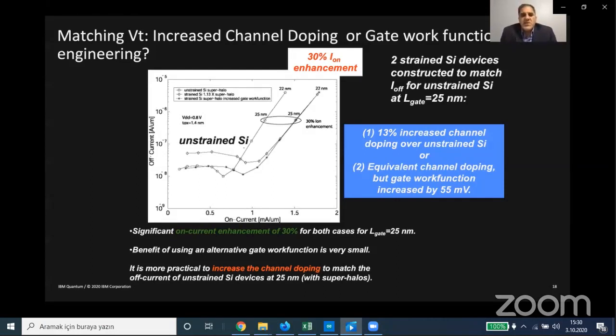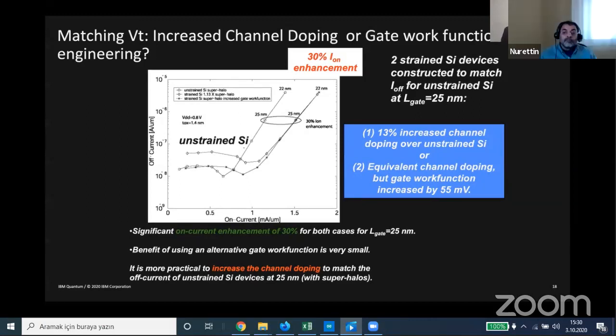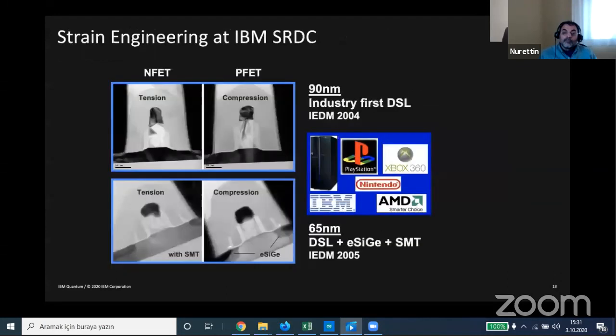And these results were presented at the IEDM conference and gave the industry confidence in using strain as a knob to boost nanoscale technology. In fact, we used this at IBM at 90 nanometer, 65, 45, 32, 22, and so on for several technologies. Shown here is the 90 nanometer. We used tensile strain in the NFET, compressive strain in the PFET. Here the strain was induced through nitride layers on top of the NFET and PFET.